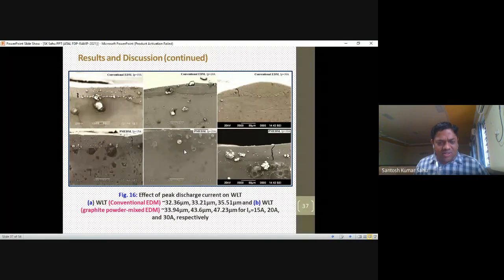Therefore, the debris remains in that same state for a longer period of time. Again, it is solidified after some time during the machining. However, after some time it can be uniformly deposited onto our machined surface, and the layer should be thinner compared to the EDM. So that's why, in our conventional EDM versus your powder mix EDM, the thickness increases in the powder mix EDM as compared to our conventional EDM.